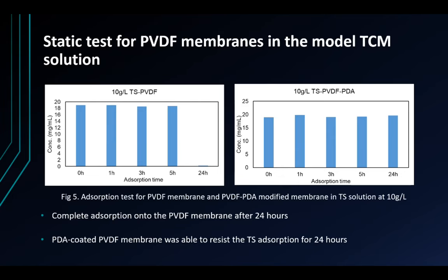We were also interested in the adsorption behavior of Janus PDA modified PVDF membrane during a static test, and we observed that the PDA coated PVDF membrane was able to resist the TS adsorption for 24 hours during the static test.